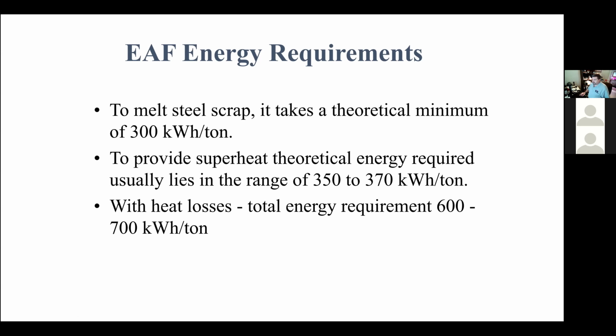And then at the caster, we want the metal to go into the copper mold and get cooled to start to solidify. So with superheat, you're typically looking at a total equivalent energy requirement of about 350 to 370 kilowatt hours per ton. But when you look at inefficiencies, and especially when we use a lot of chemical energy, we produce a lot of hot gases, and we can't effectively recover all of the energy from those hot gases. So we have some inefficiencies. You'll see that the total equivalent energy input in electric furnace steelmaking is typically about 600 to 700 kilowatt hours per ton.